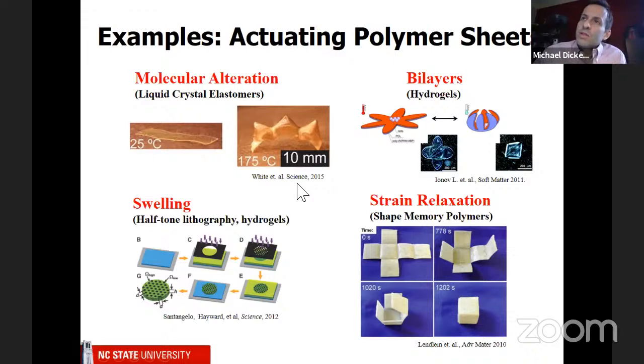So there was some really nice work about 8 years ago now that used these materials that can swell. They're gels, hydrogels, and they were patterned with light. So this is showing a mask using little holes to create regions where the light can hit the material, and wherever the light hits the material, it becomes stiffer.